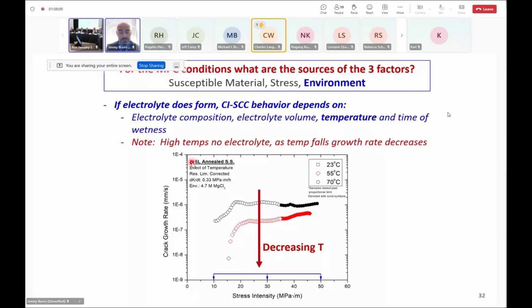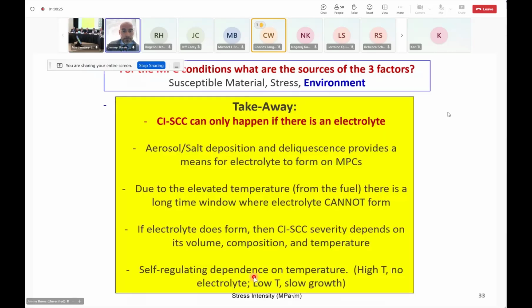At very high temperatures, you can't get an electrolyte because it's not thermodynamically stable. Well, once you get it, then as the temperature continues falling during the course of operation of these components, it starts to decrease the crack growth rate, or decrease the susceptibility or the intensity of this chloride-induced stress corrosion cracking. So what are the takeaways we have here, okay?